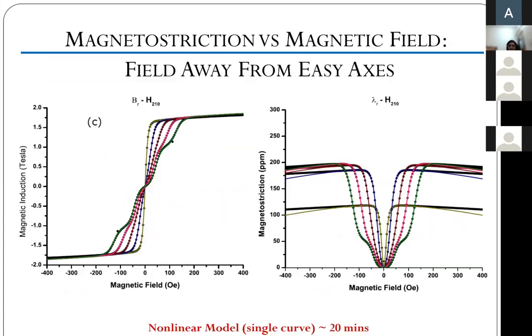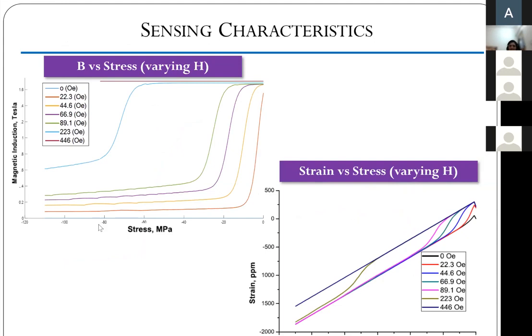And then we also did, so this is called the actuation behavior. When we apply a magnetic field and magnetostriction is generated, this is the actuator response. There is also the sensing characteristics, where we apply stress and look at what happens to strain and what happens to the magnetic induction. Clearly, even with stress, there is a saturation that happens. We keep increasing the stress for varying magnetic field values. In this case, the same thing again, we keep varying stress for varying magnetic field values, but look at what is happening to strain.